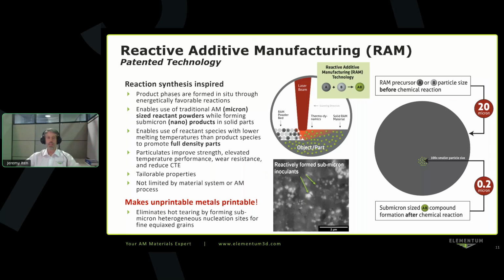Not only does it make many alloys that otherwise would be unprintable printable, but it allows you to improve and tailor the properties towards your applications. This is one of the few ways, for example, that you can really improve the modulus of your materials. Modulus, your stiffness, is something that's very hard to change within a given alloy without completely changing your alloy. But adding in ceramic particulates, making a composite type material, can have a significant effect on your modulus. You can significantly stiffen your material with relatively small compositional changes.